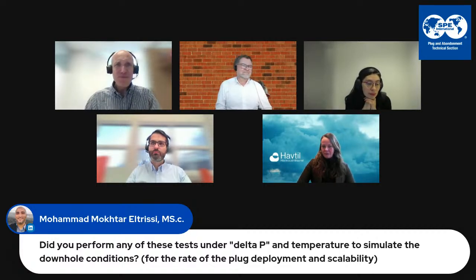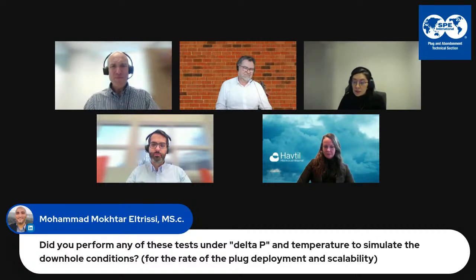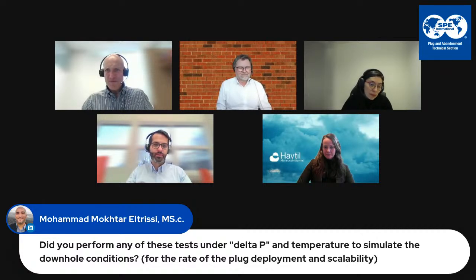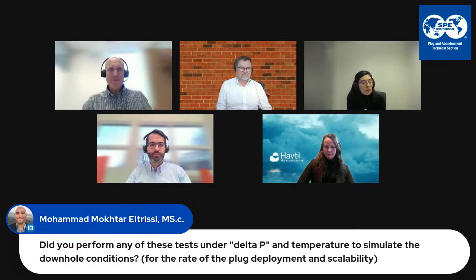Yeah, so for the pressure differential that we applied, it even surpassed, for example, the case that Aker BP had at Valhall. So we're confident that we tested a pressure range representative for downhole conditions. And in terms of temperature, I believe so as well. But our concern was not a particular bottom hole temperature. For a while, we were more concerned about testing the whole temperature range for our particular alloy. So we tested from 20 degrees to 120. Not sure if you're gonna apply it at 120, but at least we know what's gonna happen with this particular one.